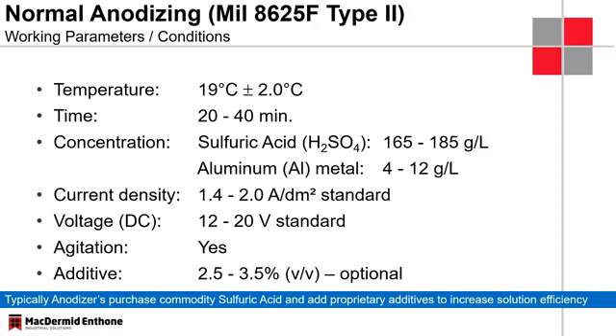A lot of people talk about sulfuric acid anodizing, type 2 anodizing, type 3 anodizing, and so on and so forth. I'll just explain very quickly the differences here. Under the mil specification, type 2 anodizing is a sulfuric acid based solution. We operate around 20 degrees C, 19 degrees C, for around 20 to 40 minutes. And we usually say we get about a micron of deposit every 2 to 3 minutes. So that would give us in this case about 10 to 15 microns. The sulfuric acid concentration is normally around 165 to 185 grams per liter.